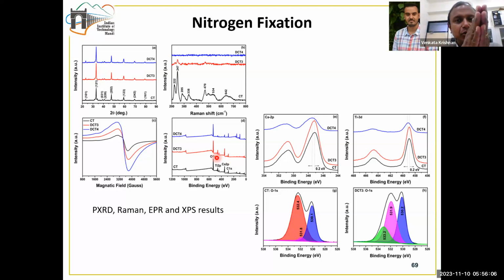From the XPS, we are able to see that titanium, which normally exhibits a +4 oxidation state in calcium titanate, shows not only the +4 oxidation state but also the +3 oxidation state because of the oxygen vacancies. This is a clear indication of the presence of oxygen vacancies. On the other hand, the EPR also shows certain signals which indicate the formation of the vacancies.